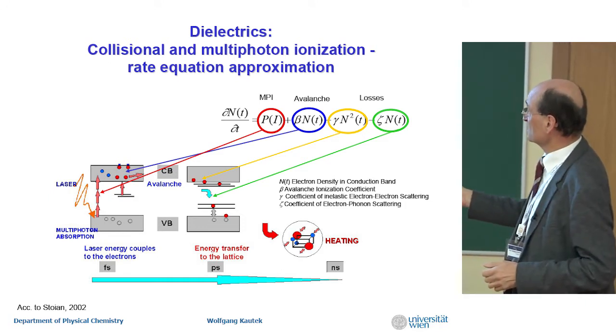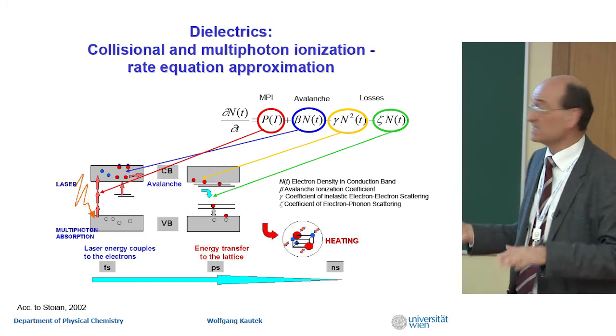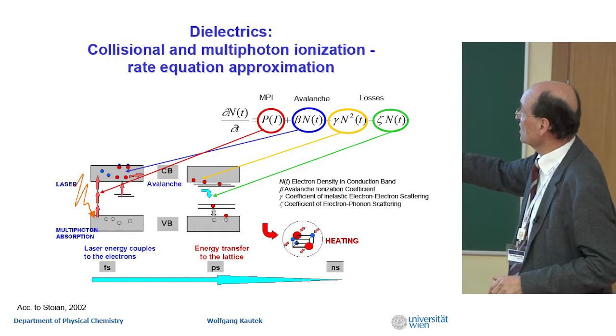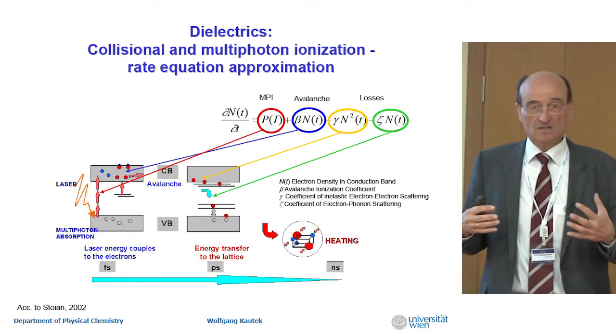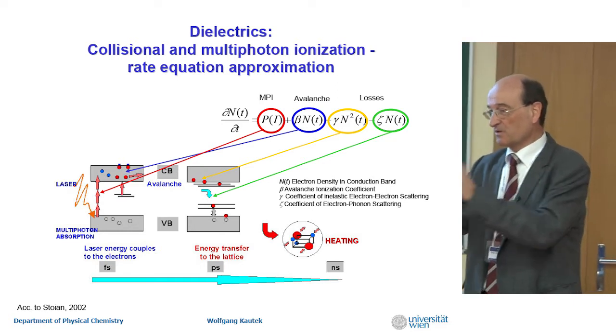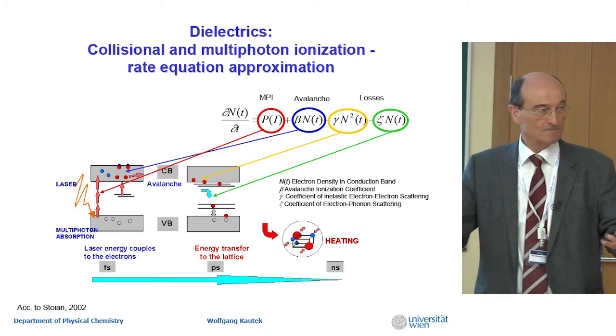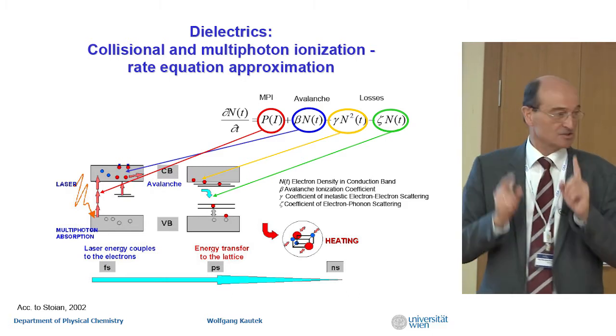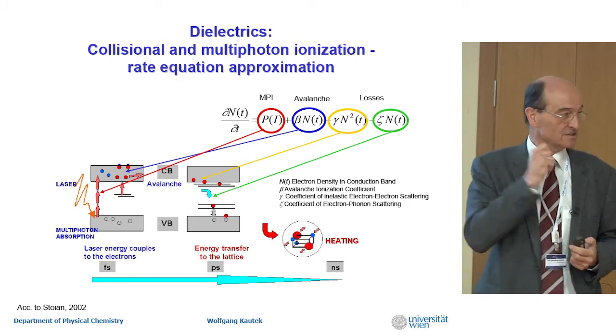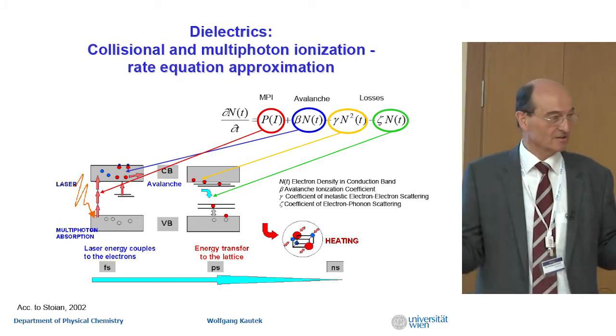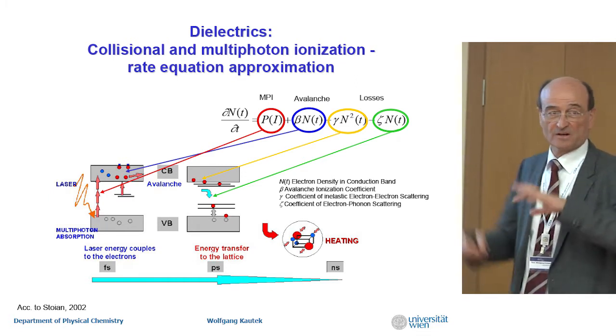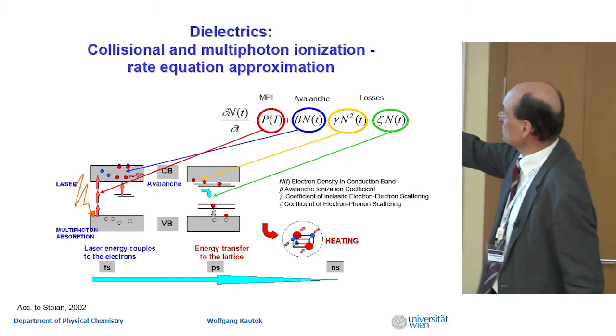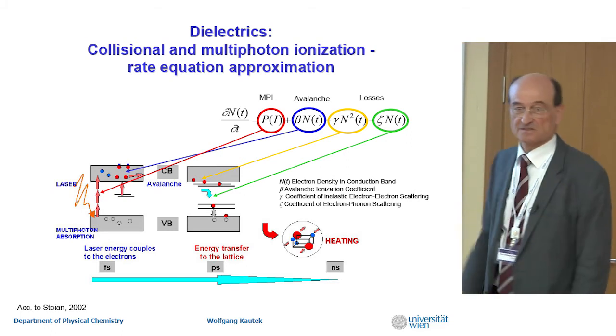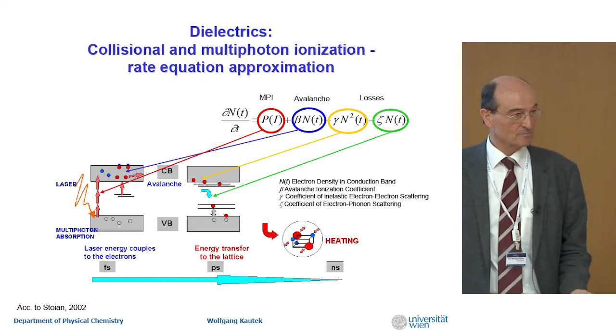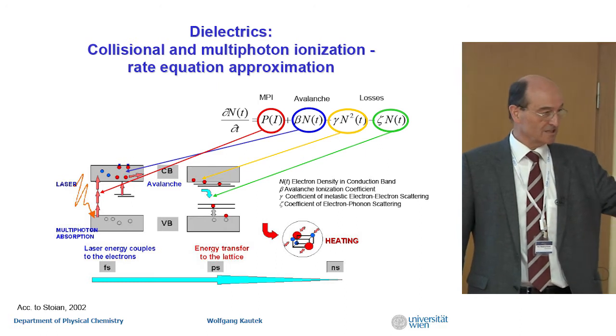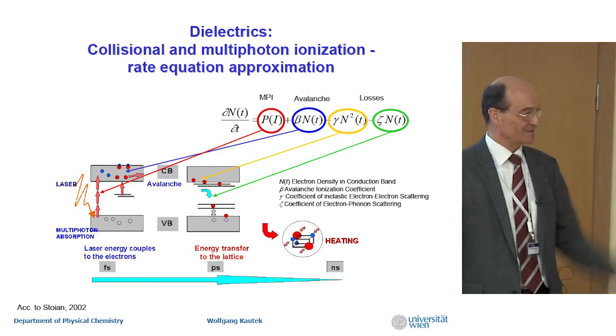If you go to longer pulses and lower intensities, then you have to make use of stochastic processes. You have to reckon with free electrons, which are there due to defects, and sometimes it works and sometimes not, and the avalanche process is stochastic, it's not deterministic. Sometimes you have an explosion, sometimes not, you know. So therefore, you remember the results were quite bad, the ablation. So we can switch between stochastic and deterministic processes. Remember, the multi-photon process is a deterministic process, and if you do, for instance, multi-photon excitation of polymers, it's deterministic. Nice results. Huh?